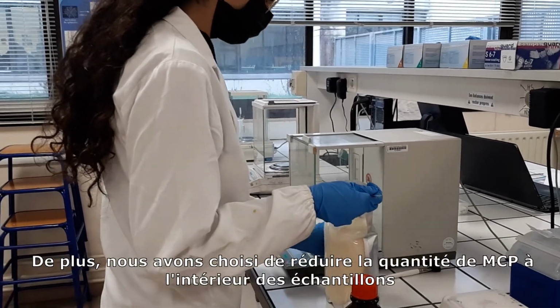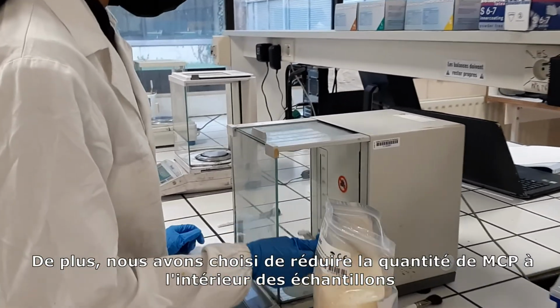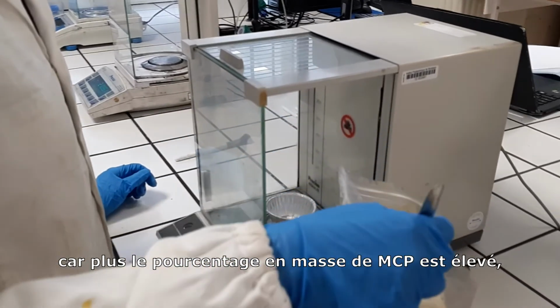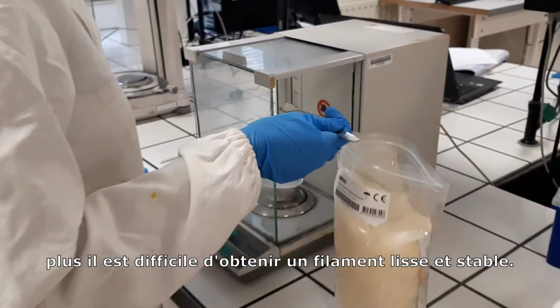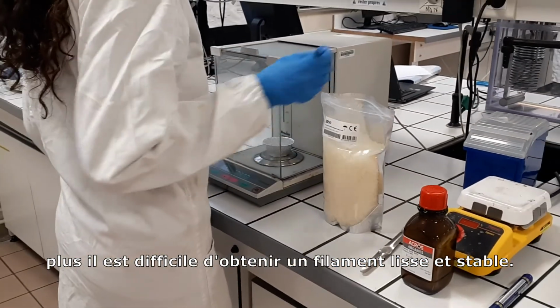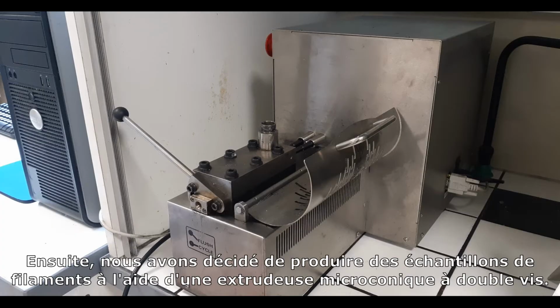Additionally, we chose to reduce the quantity of PCM inside the samples, as the higher the weight percentage of PCM is, the harder it would have been to obtain a smooth and steady filament. Following, we decided on producing filament samples using a microconical twin-screw extruder.